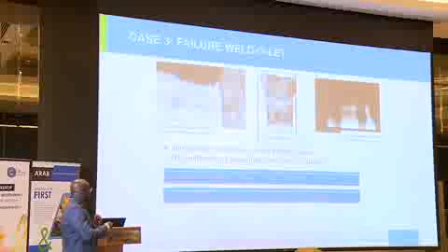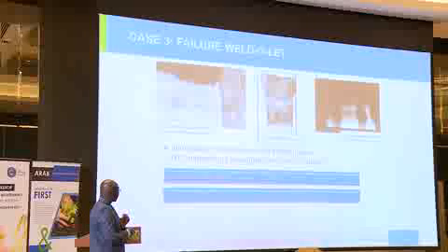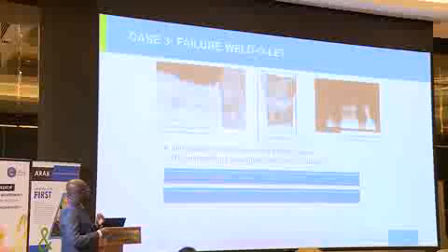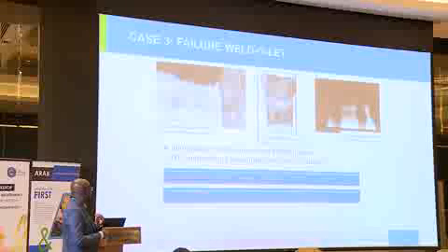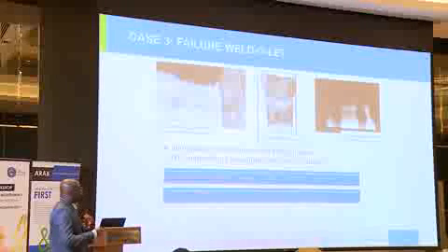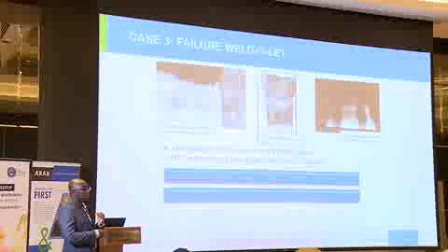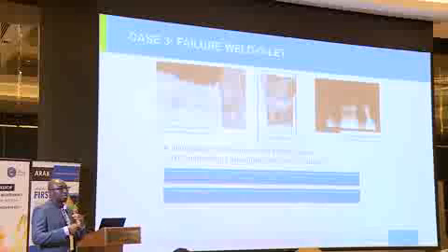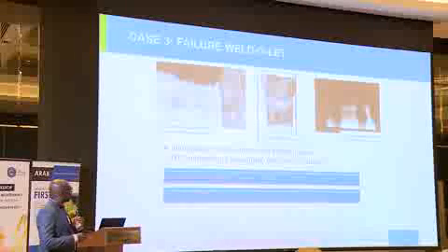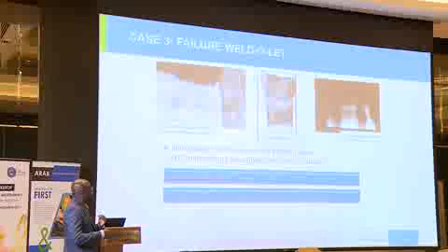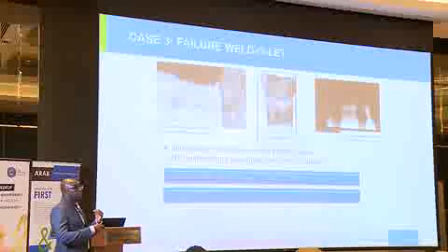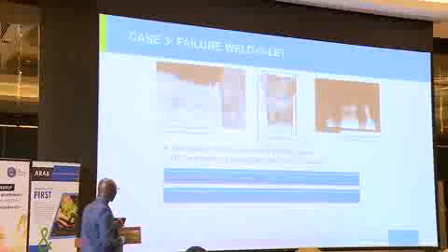What this triggered is that the plant now had to check for all the other weldolets they have in the synthesis section, that do they have the correct material of construction. The other thing is that actually you do not need to have your plant off-stream to be able to do something like this. You can actually do on-stream X-rays. And you have to bear in mind that when you do this, you are not looking for cracks, because that can be quite tricky depending on the orientation. But you are looking for loss of material, which will be evidenced by the shading that you will get based on the density. So you can actually detect on-stream whether you have a problem with your weldolets.